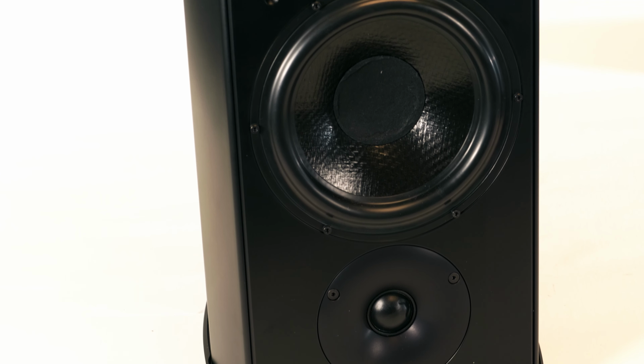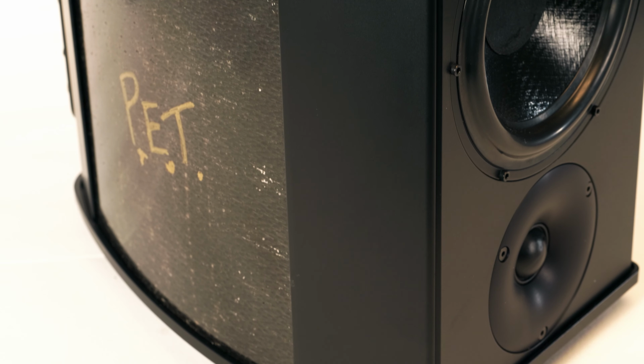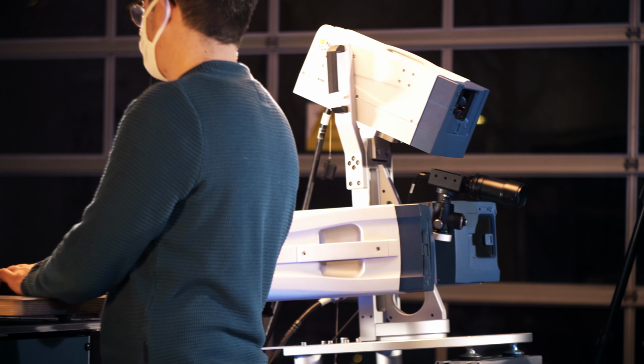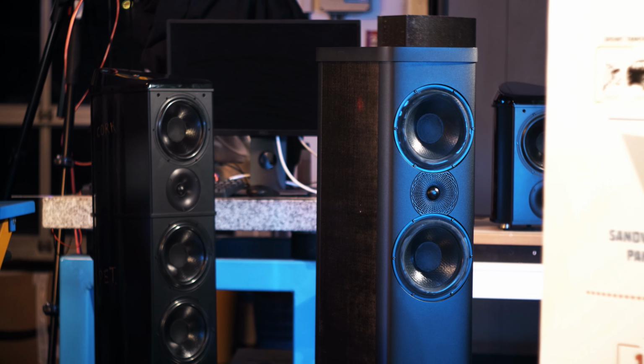The fourth application targeted within SSUCHY is the high-end acoustic sector. We developed a green loudspeaker whose structural part is a monocoque cabinet component. It is initially made using RTM with a U-shaped cross-section made of carbon fibers, glass fibers, epoxy matrix and PU foam. The main requirements are linked to the vibroacoustic behavior, the production cycle time, the recyclability, sustainability and costs.